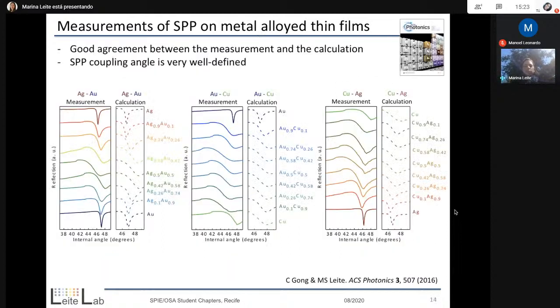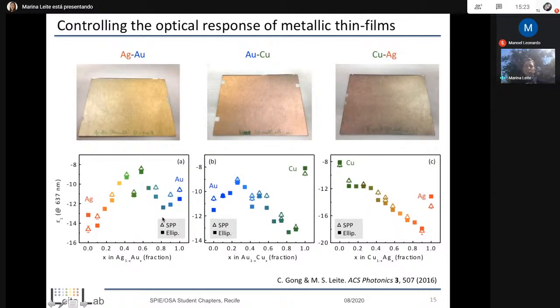So now I'm showing you all of our SPP measurements using the Kretschmann configuration for the binary mixtures. Again, on the left, you're seeing the measurement, and on the right, the calculations. You see a very good agreement between the two. So we could basically see how much shift there is. And then what we did, at least for one wavelength, was to determine epsilon 1 and compare our measurements with our completely independent ellipsometry measurements. And then we found a really good agreement.